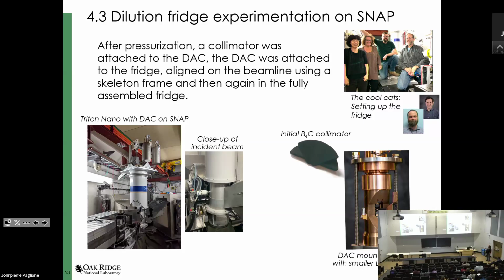But overall, another interesting thing we learned was that the initial collimator was this 3D printed collimator I showed you earlier, which is made from boron. And with this setup, we actually see some beam heating. Without the beam on, you can cool that cell to 50 millikelvin. With the beam on, we were only able to get to 200 millikelvin. And the current scenario is that the gammas that come out of the boron when it's hit by the beam hit the cell and then warm it up.